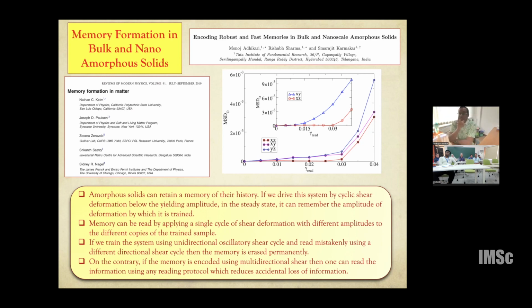So here the interesting point was that if you do multi-directional oscillations, then you can read in any protocol you choose, and the memory is not going to be erased. But if you do it in one direction and mistakenly read in the opposite direction, then you can actually erase the memory. Okay, that's very interesting. Yes, so this is what we showed. Let's say you do XY oscillations to encode the memory, and then you mistakenly do an orthogonal XZ, then you have erased the memory and you could not recover it. But if I do XY, YZ, ZX, and then read and store the memory, then I can do any one of the methods, and I will have the same information without losing it.